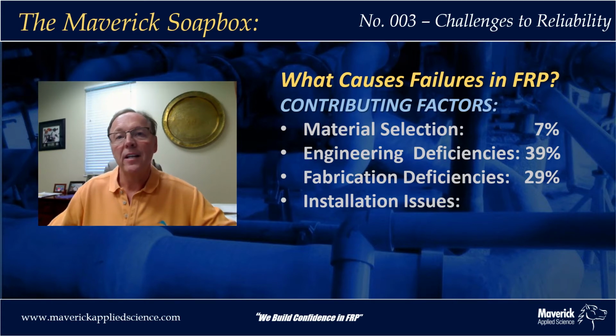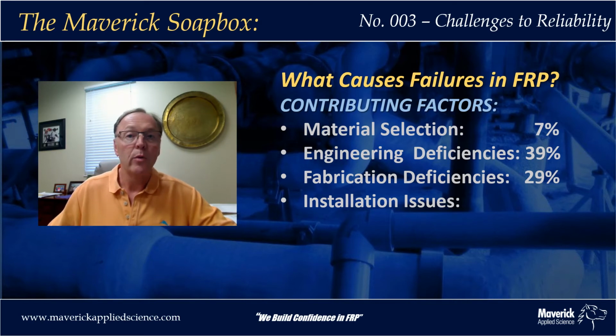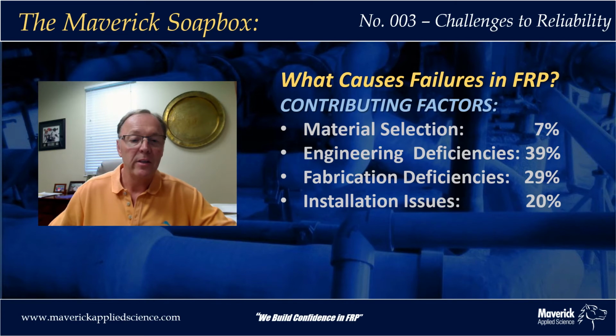The next contributing factor that we identified was installation issues. Installation issues might be poor alignment in pipe joints, flange failure due to over torquing, unqualified laminators and bonders, and improper pipe supports, which would all be examples of installation issues. Of those, installation issues were found 20% of the time in the cases examined.